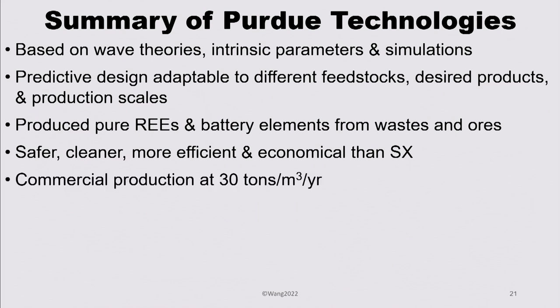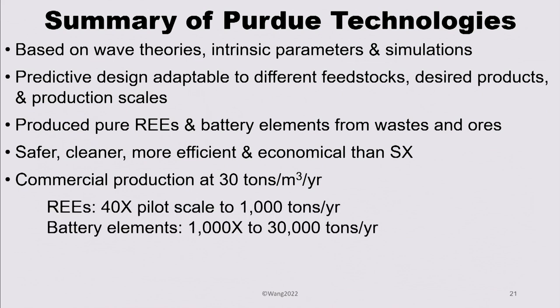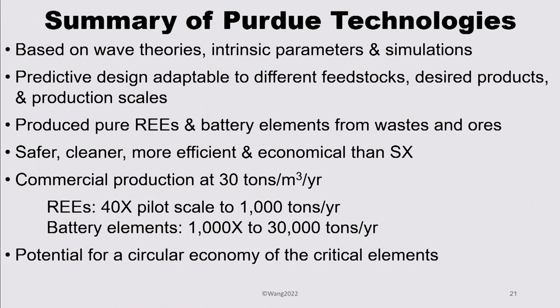solvent extraction. And in commercial production, at the productivity of about 30 tons of these elements per cubic meter per year, that means to build a typical rare earth plant of 1,000 tons per year, we just need to scale up from the pilot to 40 times larger. For battery elements, for 30,000 tons per year, we need to scale up 1,000 times. And we're confident that this will succeed to scale up into the commercial scale.